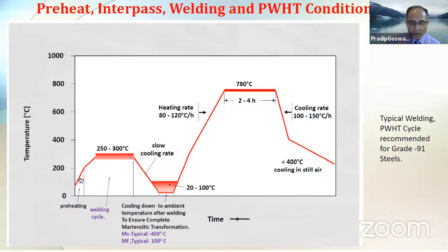So from all aspects, it is recommended that this alloy should be preheated, a very strict interpass temperature should be maintained, and after completion of welding, it should be cooled down to the ambient or room temperature at a slow cooling rate. Once it is at the ambient temperature, this particular time frame is when you are allowed to do any kind of inspection or NDE on this alloy.